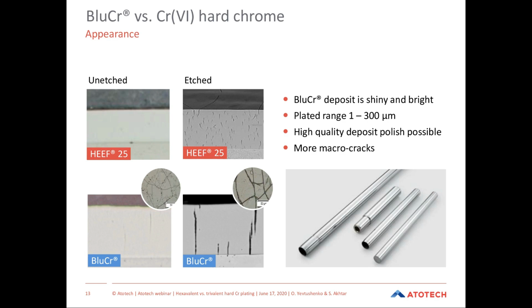If you have a look on the left side of the presentation, you can see here we compare cross sections of chromium layers for hexavalent chromium process HEEF 25 and blue chrome. So you see, if you have a look at the unetched cross section, in case of HEEF 25, you will not see any cracks going through. If you can see the etched part, some tiny micro cracks are present, which provide also good corrosion resistance.